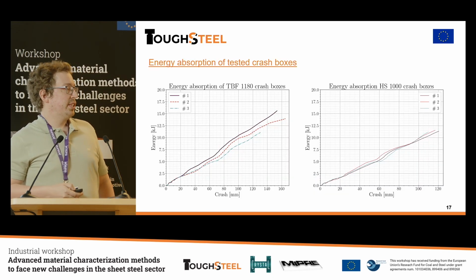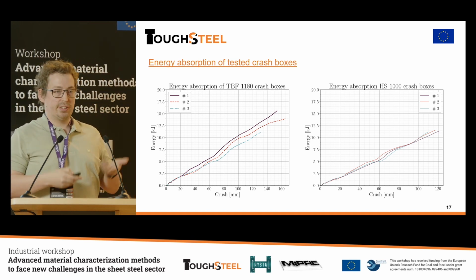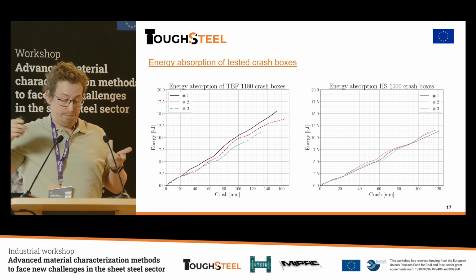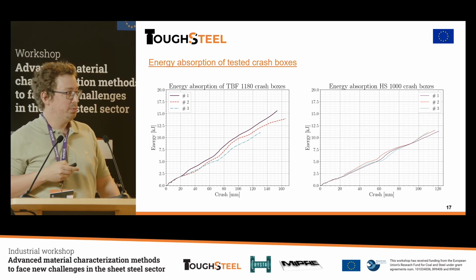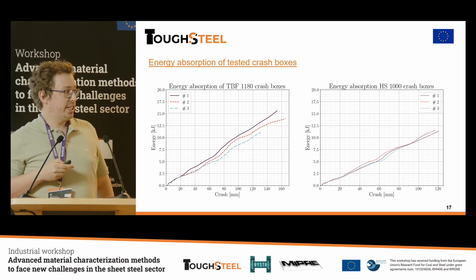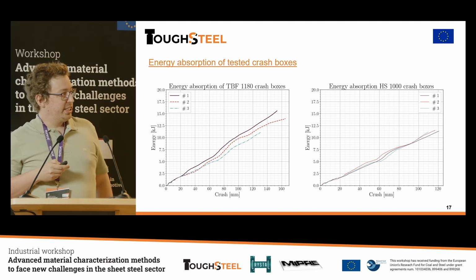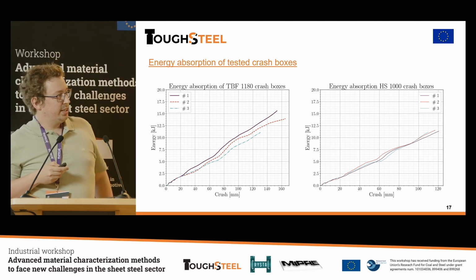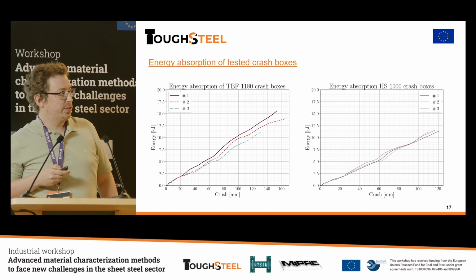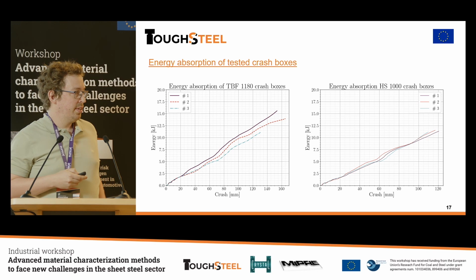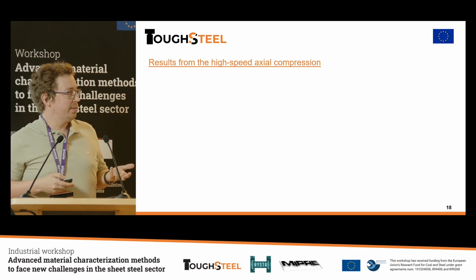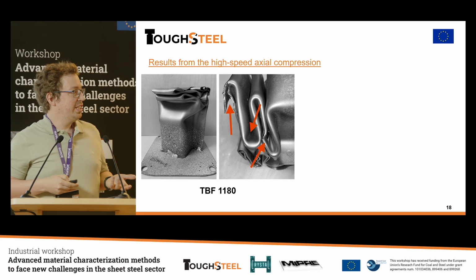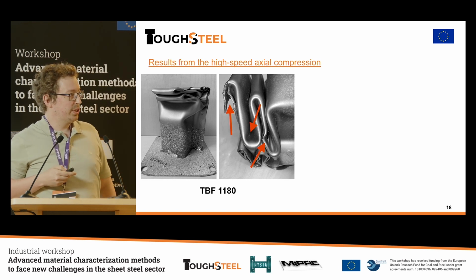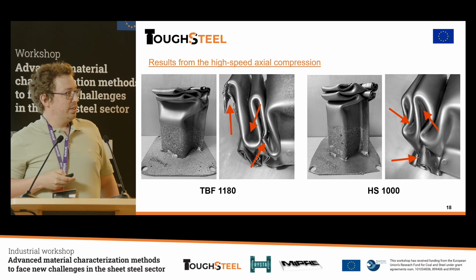So by doing this, of course, we get the usual information. You get the force-intrusion, force-crush curves, and we can integrate them to get the energy absorption as a function of the crush depth. And as you can see for the TBF material here, we have quite scattered values and quite consistent values for the hot stamping crash boxes there. And how come it is like this? Well, cracking, right? For the TBF material, we could see quite severe cracking in some areas there, and for the hot stamping steel, a lot less cracking.